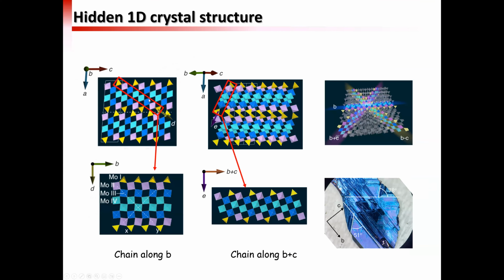So it's actually made up of the molybdenum oxide octahedrons, and they are not 90 degrees apart. Then you can see it formed a two-dimensional network, but you can still separate them. For example, this is the chain along the B direction here, and then the chain along the B plus C direction here. But if you see the structure, it's really difficult. Then you may ask why you want to separate the chains along this specific direction, right? I can still do other directions.